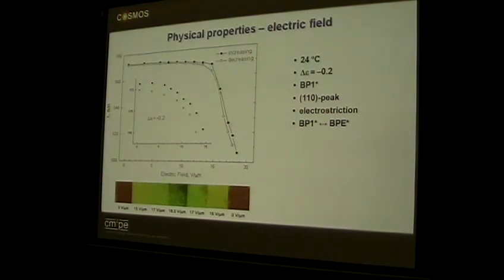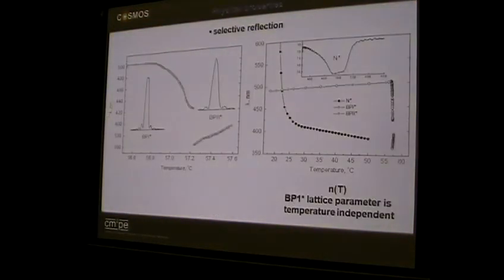I'll show you this spectrum in a minute. If you want 80%, 90%, even 100% reflection, you put two devices, left hand and right hand together. So you can make a perfect reflector for a particular wavelength of light. Okay. What kind of wavelength of light can you get? Well, the blue phase one is fairly narrow, that's probably a typical spectrum. This is just showing that kind of data for another material, slightly different wavelengths, where I'm switching from green down to blue, I'm switching down to 410 to 420 nanometers, so I'm switching from a reasonable level of green down to blue. Okay? And that's just showing you that on a slightly different scale.